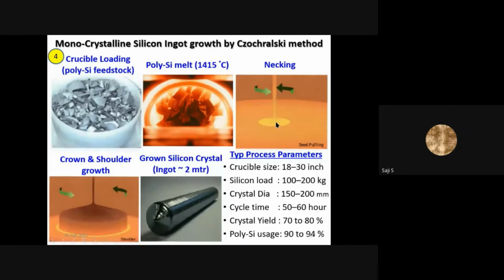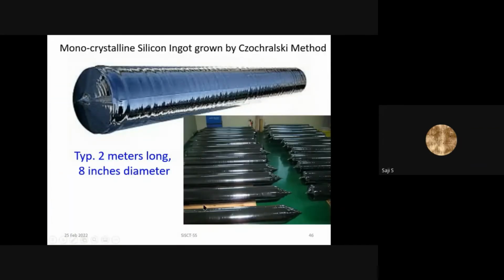You put a seed crystal in the melt, slowly rotate it and lift it up. You get a rod, a monocrystalline silicon rod of almost 2 meters long and about 8 inches. It's a very slow process. It takes about 2 or 3 days to grow this kind of rod. But you can get such rods, which are almost 8 inches in diameter and 2 meters long. So this is a monocrystalline silicon rod grown by the Czochralski method. It's a standard process of growing single crystal materials.